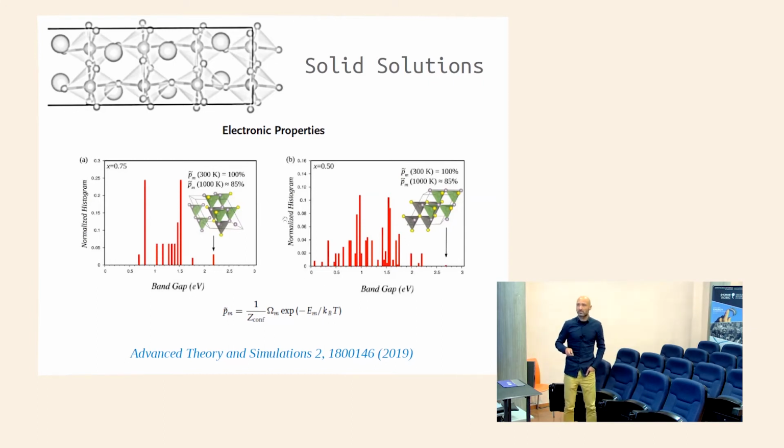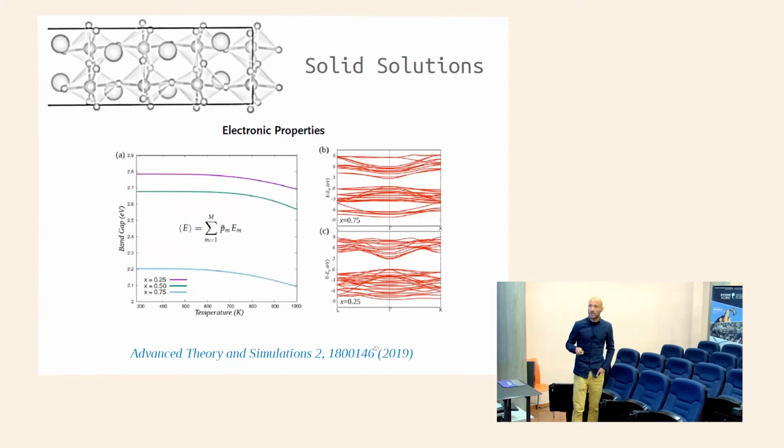What does it mean? This means that just considering configurational effects, when you now calculate the energy bandgap of these materials as a function of temperature, and again, I'm neglecting any electron-phonon or any vibrational effect here, just configurational effects, we have that with temperature this energy bandgap tends to decrease. In principle, since they are already within the interval of 2 to 3 electron volts, this seems to be a very nice, positive result, right, because these 3 compositions that we decided were stable in reality